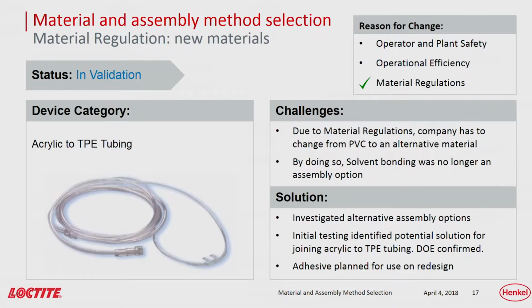So we're going to revisit the case history we talked about earlier. If you remember from several minutes ago, we had an OEM manufacturer that was having difficulty getting consistent pull strengths on their tube set assembly. They had recently done a material change strategy and eliminated PVC as a material of concern. They switched from PVC to a TPE grade, and they were struggling with assembling the TPE to an acrylic connector. Because of that, the change would not allow for consistent bond strength. And so they had to look for alternative methods.